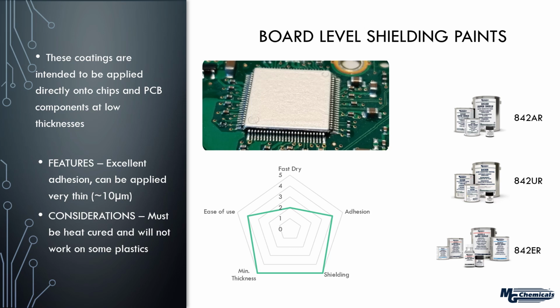So these have excellent adhesion, and typically they can be applied very thin. And I put about 10 microns, but realistically you could probably push around 6 or 7 microns. So that makes them very ideal materials. However, the one caveat I should mention is that these must be heat cured, and some of the heat curing temperatures are exceedingly high, and so that actually rules out certain types of plastics that may warp at these high temperatures. So just something to think about.